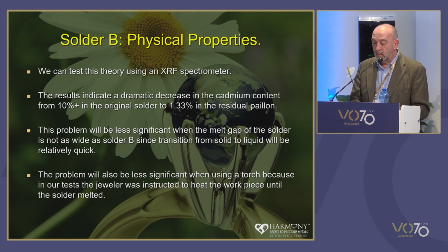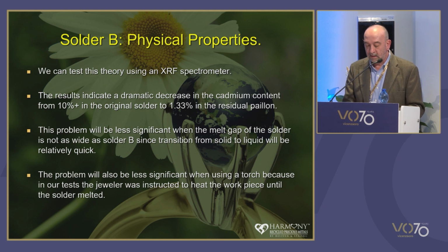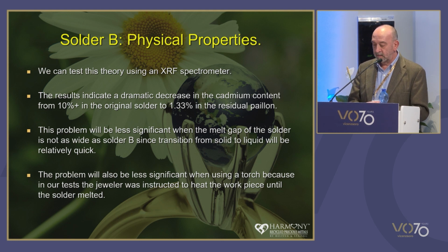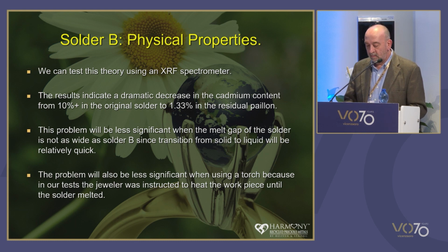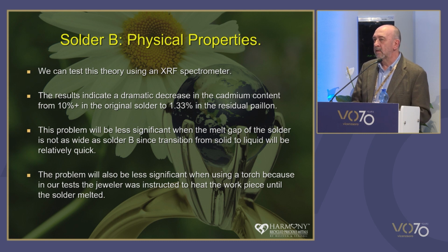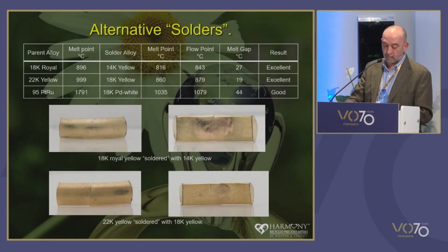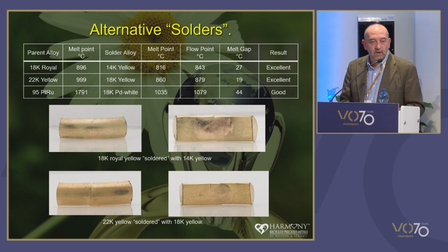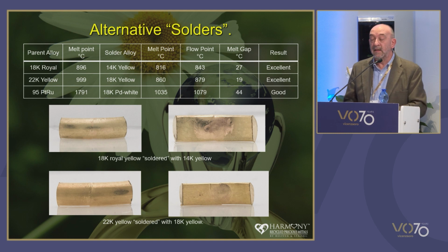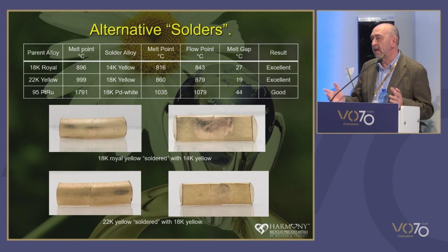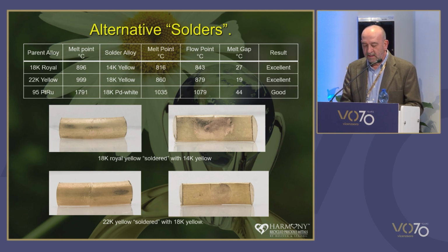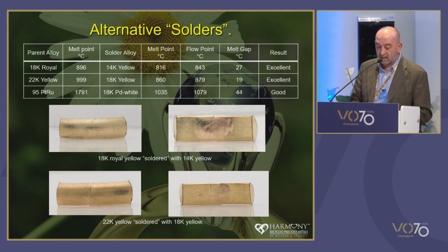So to test this, we took combinations of standard jewelry alloys and put these through the ring sizing tests. So the tests were performed using the jeweler's torch only on this because the melting range of the standard alloys that we were using was actually too high for our solder furnaces. And we got some good results. So we used straight 14 karat yellow gold to join 18 karat yellow gold. So this is just normal 14 karat sheet, 14 karat wire, and we decided to use it as a solder, and it worked very, very successfully. You could arguably say that's one of the best results in the entire test, even better than the solders.